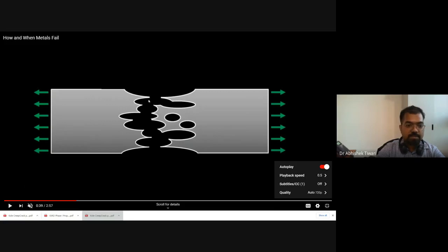So as we have discussed before, because you have these voids and the breakup on the surface, you see these dimples. And also these extended parts will look like fiber. So this area, if you look from top, will look like a rough surface. So you will not see this kind of surface in fatigue fracture. Fatigue fracture is usually a flat fracture. Okay, so this you will see either in ductile fracture or in creep fracture, this kind of microstructure. So the fracture surface structure is called a fractograph.